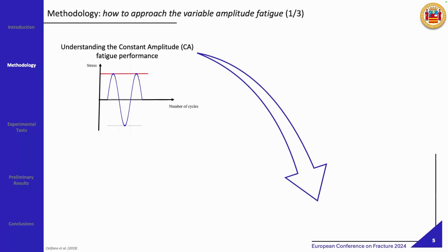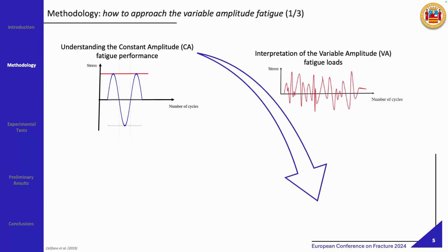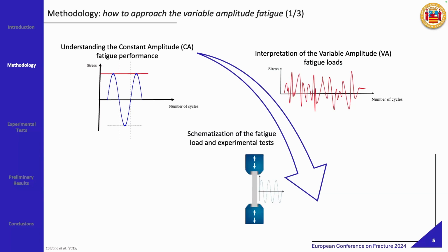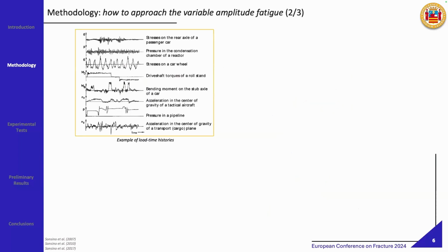First things first, we want to understand the constant amplitude behavior of a given material we want to study. The second step is the interpretation of the variable amplitude loading that we want to take into consideration. The following step is how to schematize this kind of load, because often if we want to carry out experimental tests, we want to simplify these loads by, for example, using counting methods. In parallel, we adopt a failure criterion which suits our needs. And finally, we compute the damage accumulation through famous and widely recognized rules.